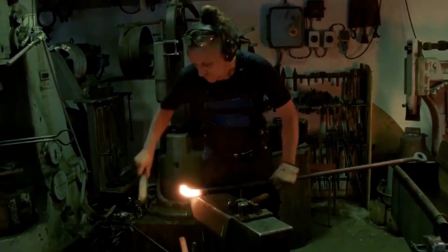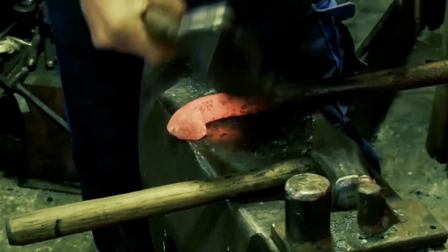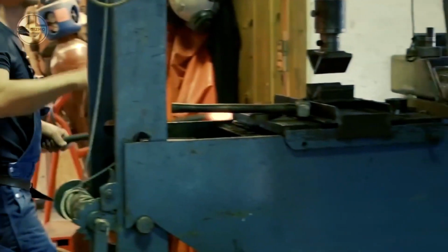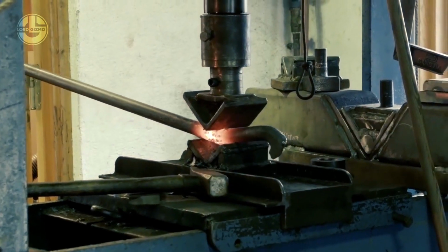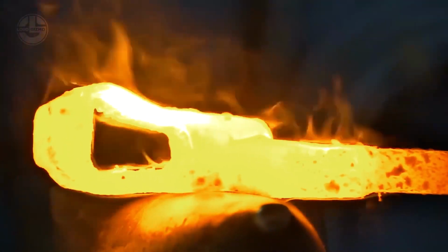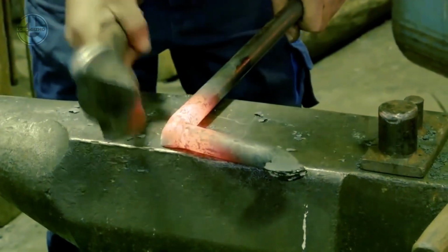Number 2. Flux. After heating the metals, this process will proceed with removing the metals from the forge and sprinkling them with flux. This will protect the metal and stop oxidation from happening, which could cause scales or slag to form on the surface and destroy the weld.